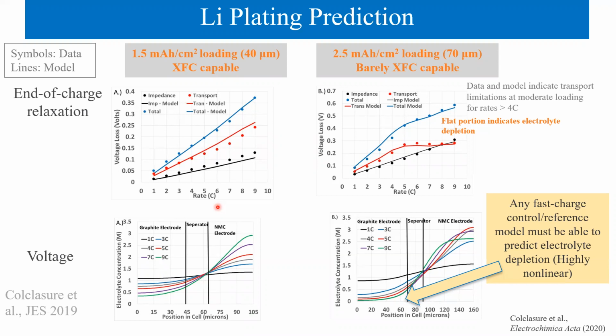While lithium plating occurs, the moderate loading cell exhibits a transport overpotential plateau at a rate above 4C, indicating the high rate charging acceptance is severely limited by transport losses. The electrochemical model fits the measured overpotential well and is used to investigate the cause of the severe transport limitation measured for moderate loading cell at high charging rate.